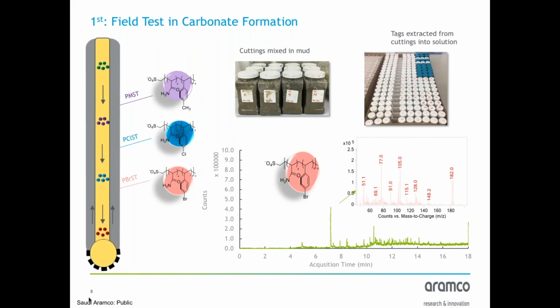The first deployment of the nanotags to label the drill cuttings in a carbonate reservoir. We successfully injected ppm levels of different nanotags into the mud line without any interruption of the drilling operations. The cuttings were tagged as they were drilled at the pit and then collected off the shale shakers. We used the developed solvent extraction and thermal separation workflow to extract the nanotags from the cuttings in the lab for the estimation of the arrival time.